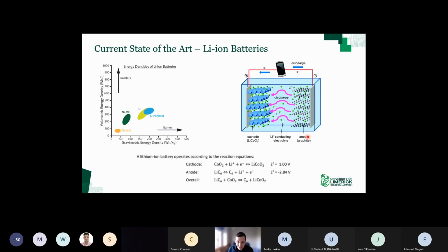At the anode, graphite is conventionally used, so the majority of lithium-ion batteries on the market today will have graphite anodes. Graphite is a really good anode material because of its layered structure. Graphite is basically layers of carbon, so graphene sheets. That layered structure is very conducive to long cycle life, because when you charge the battery, lithium migrates from the cathode across the separator and into the anode, and it intercalates between those layers, and that's not disruptive to the structure of the graphite. It means you can do that reversibly over thousands of cycles with little capacity fade, at least related to the structure of the anode.